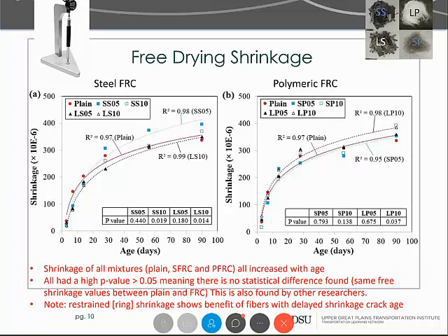And then if we look at the statistics again, if it's 0.05 or less, that means we found a difference, and most of these were higher in this case, meaning there was not a difference. There are a few exceptions, which is the SS10 and the LS10, which are both lower. So it's possible that the steel has a little bit more of a difference. This is one that has been researched a lot, and there's mixed feelings in the literature. Some people say it does change it, and some say it does not. But in general, most people have commented that when you have less than 1% volume fraction of fibers, you don't usually see an effect of having the fibers in the concrete.